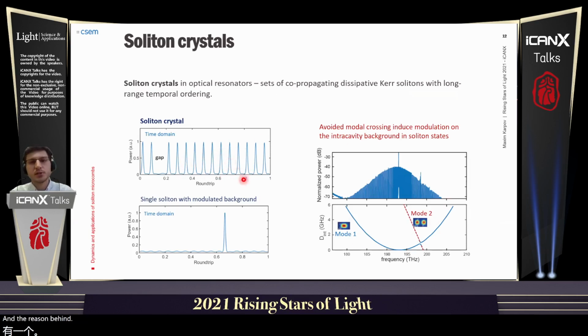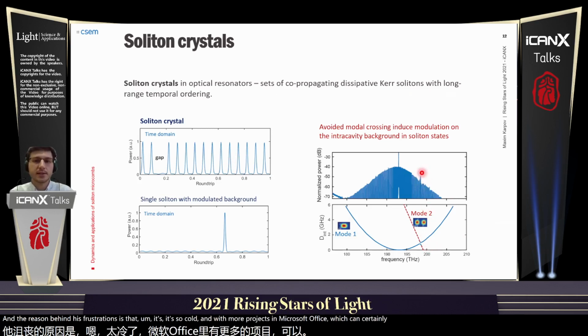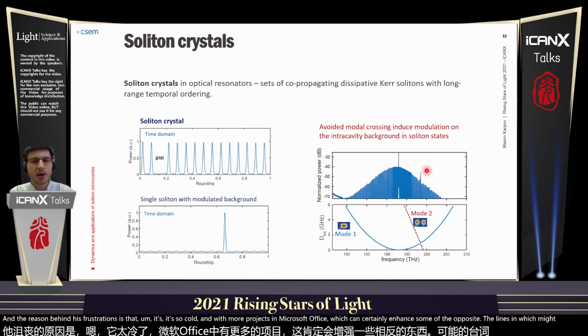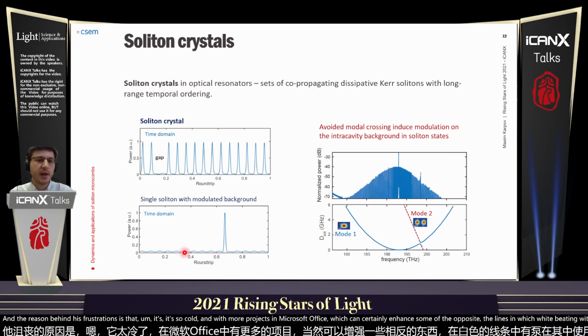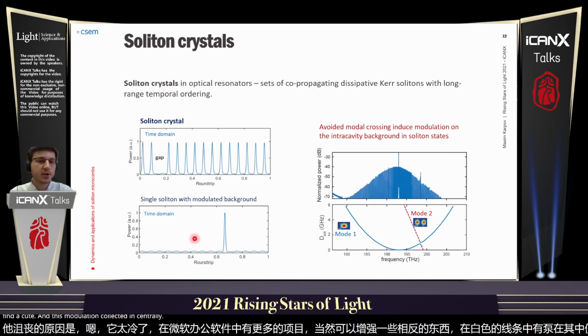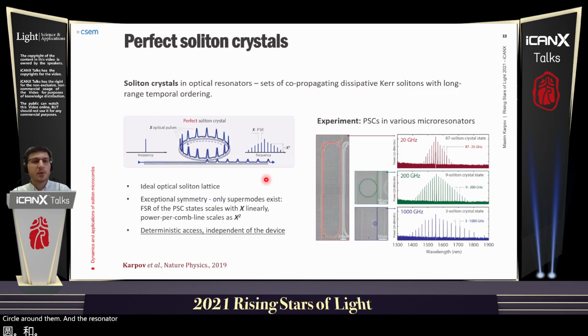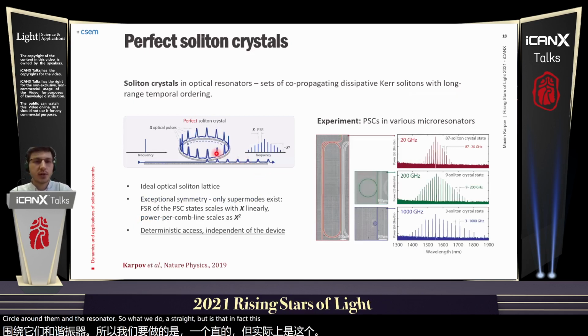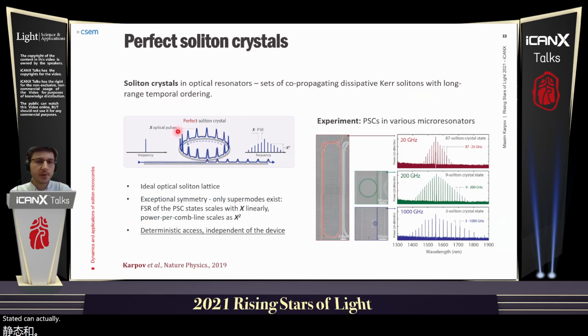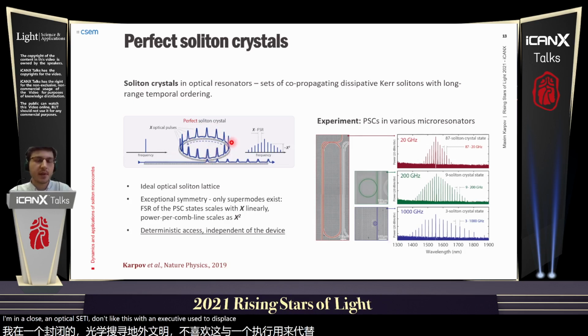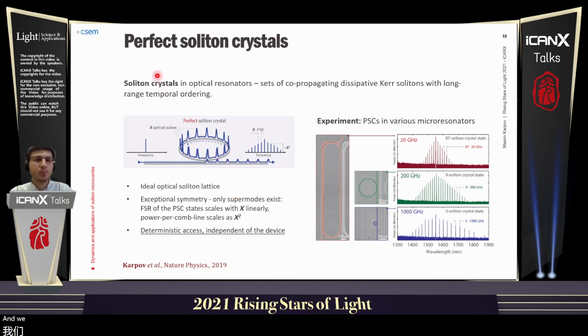The reason behind these formations is so-called avoided mode crossings in microresonators, which can selectively enhance some of the optical lines, and which, by beating with the pump, can induce a certain modulation on the background inside the cavity. This modulation can pin the solitons in place and hold them as they circle around the resonator. What we demonstrated is that these soliton crystal states can actually fully fill the cavity, forming a so-called closed optical soliton lattice with exactly equidistantly spaced solitons. And we call these states perfect soliton crystals.